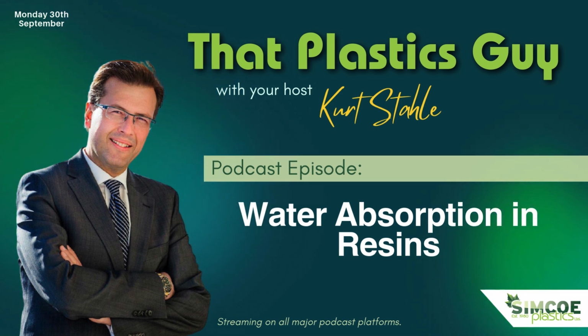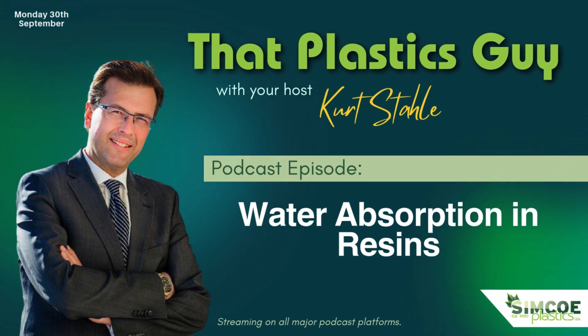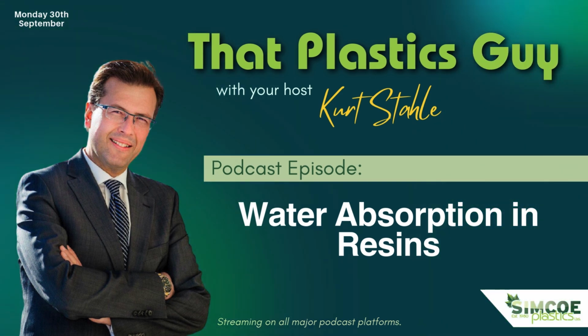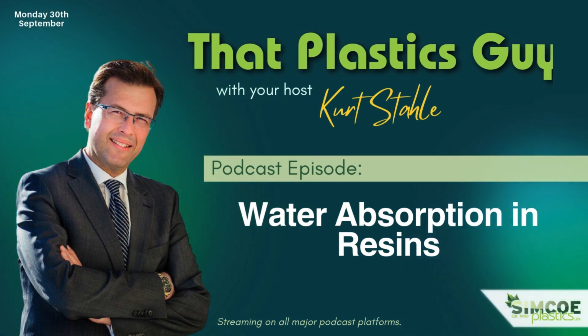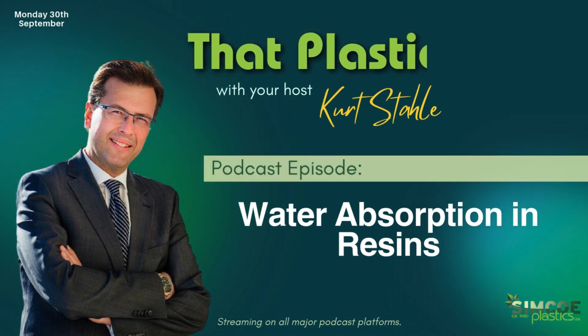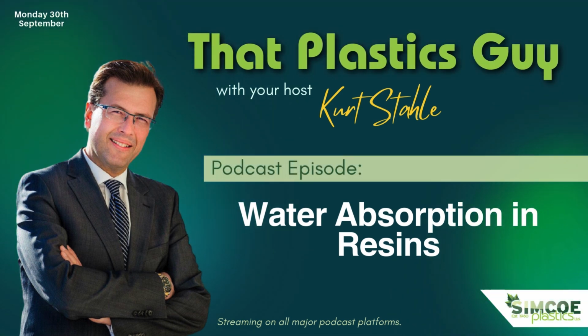So the use of moist acrylic material, for example, in injection molding, causes the molded parts to have poor surface quality. Wet acetal can lead to changes in dimensions, for example. PET and PBT materials can lead to shorter chain molecules from hydrolytic decomposition, which results in a significant deterioration in the mechanical properties of the material. And of course, in nylon, I've mentioned the presence of moisture really impairs the impact strength and the mechanical strength, and you have to let the parts recondition.